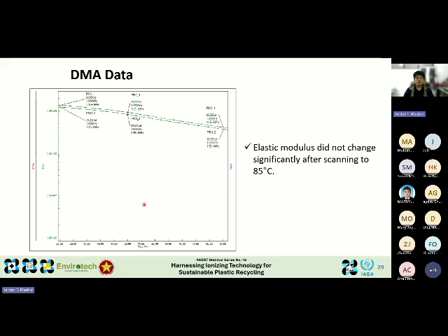Hopefully not. This finding indicates that the samples prepared at Envirotech are able to retain their stiffness and structural integrity even at 85 degrees Celsius, elevated temperatures. In other words, they're robust enough to withstand real-world outdoor conditions without significant change in their stiffness.